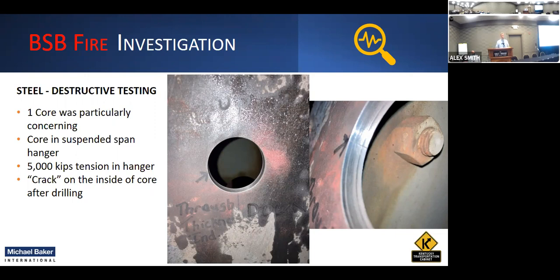The people doing the drilling have done this many, many times over a career, and they've never had a notch or a crack pop out of this. We're still not sure exactly what happened here, but it was of major concern to us when this happened. And it caused us to ask, are we in danger of having this entire hanger fracture or some other thing occurring here that we need to be more cautious of? And then we actually went back and shut river traffic down, on account that we could drop this suspended span if this hanger were to fracture.